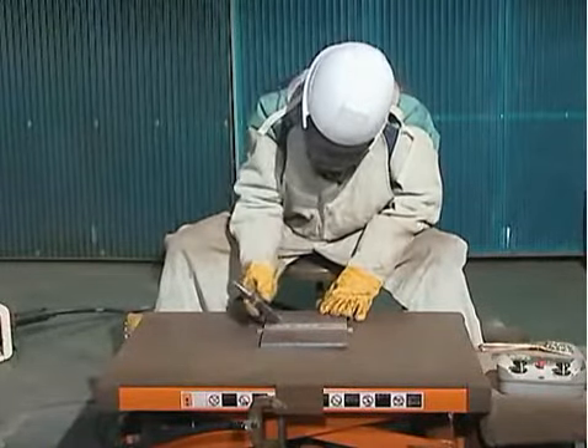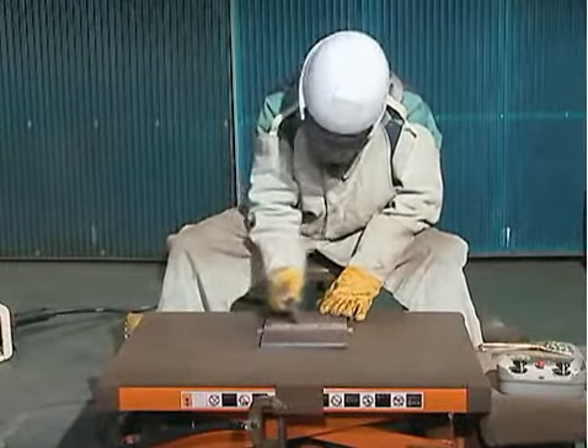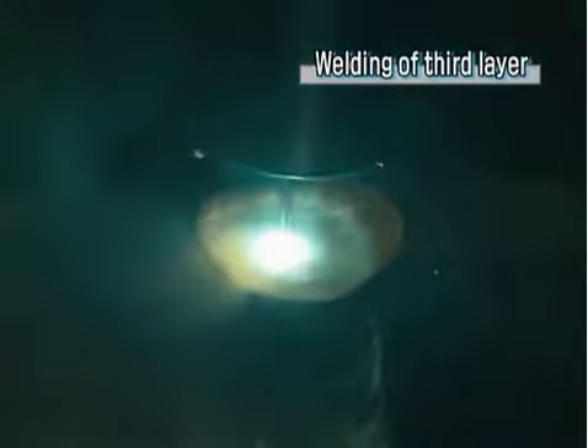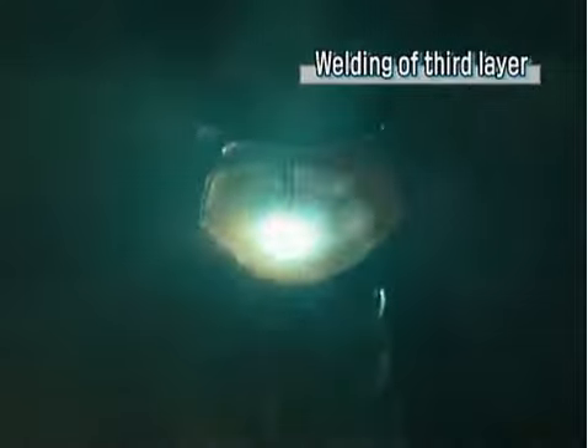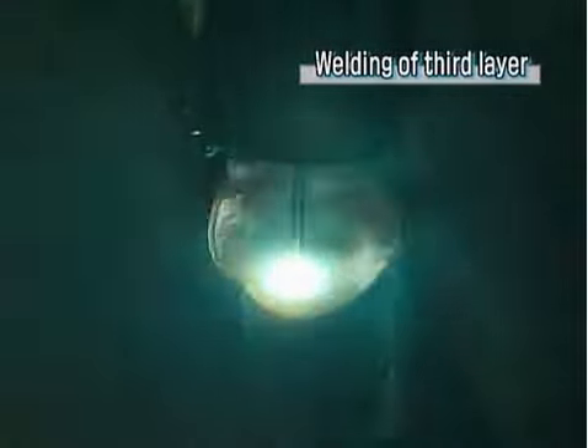Clean the surface of the second weld layer. For the third layer, use a forward push method, weaving side to side the full width and finish in one pass. The bead width should be wider than the groove width by 2 to 3 millimeters on each side, and the weld reinforcement height should be about 2 millimeters in the center of the bead with a gently rounded weld reinforcement.